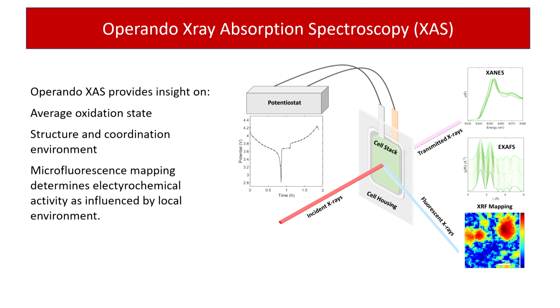So I want to turn to X-ray absorption spectroscopy and point out that multiple characterization tools, when brought together, can lead to profound insight into what's happening in the battery. Operando X-ray absorption can provide us information about the oxidation state through XANES. And XAS is also not dependent on long-range order, so you don't need highly crystalline materials to gain insight. By using EXAFS, we gain information on the coordination environment and structure of the materials.